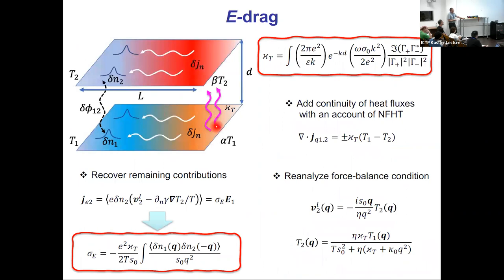And then, as I said, there will be thermal imbalance between these two sheets, and you can calculate an interlayer near-field effect. So the interlayer thermal conductivity, also due to Coulomb interactions, can be calculated and expressed again in terms of the intrinsic conductivity of this fluid, if we are interested only in the regime of charge neutrality. A similar expression exists for the energy drag component of drag resistance. The key part is that it has an opposite sign. And so when you promote this to finite density, the competition of these two mechanisms explains the sign change and non-monotonic dependence of the drag resistance.